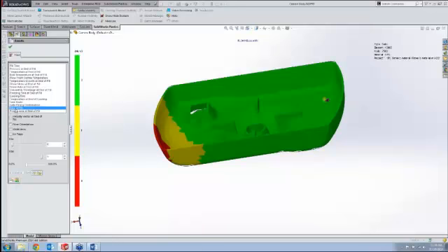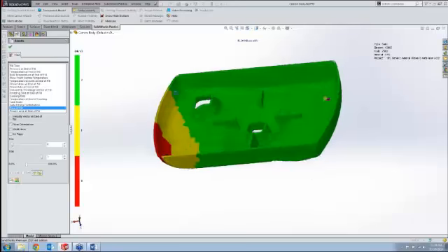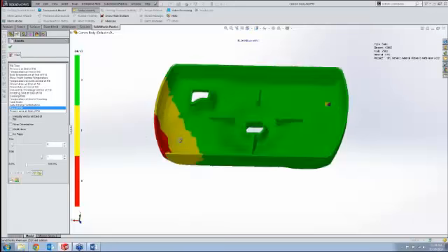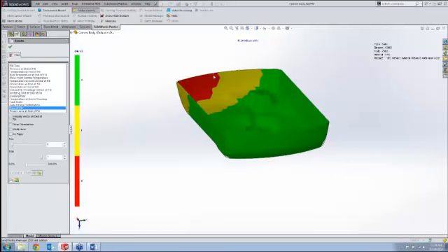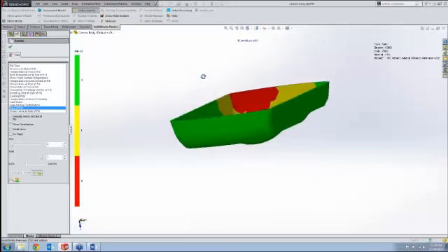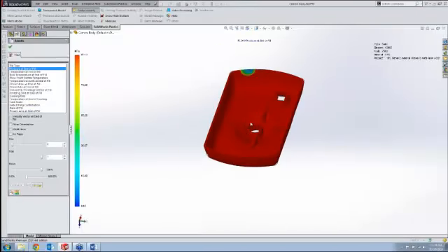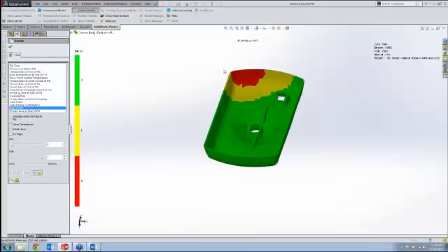The ease of fill is a 3-color coded plot that shows you what areas on the mold were easy to fill, what was getting difficult, and what was nearly impossible to fill in the red zone here. Obviously, in this case, this is the last portion to get filled, so you're going to see a red spike there. But if we go back and look at the pressure at end of fill, we're pushing up to 92 MPa, and I said that the limit on this machine was 100 MPa. So we're nearly maxing out the press, specifically in this red area right here, trying to get that to fill. And more than likely, if we have any additional issues, this is where a short shot's going to occur.